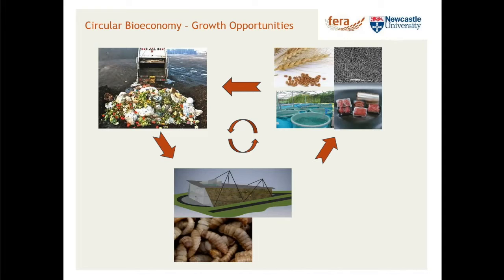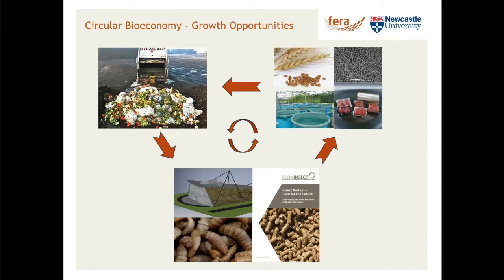So there's a lot of interest in things like black soldier fly larvae as a source of protein at this stage, mainly for sort of aquaculture or animal feed, but could well be human in the future. So we can use this material as a source of protein and oils. We can also extract chitin out of the larvae, convert it to chitosan. And so from this process, we can get potentially packaging materials of various types. We can produce nanofiber films, which I'll talk about in a moment. We can feed these things to fish, and we can also potentially use these materials as a substitute or replacement for pesticides and fungicides on our crops and seeds, which would be quite nice as well. And then having grown and processed and used some of these things, we can recycle and instead of dumping, feed it back. So we've got the basis of a circular economy based around biopolymers. So this is an interesting direction which we may well be heading.